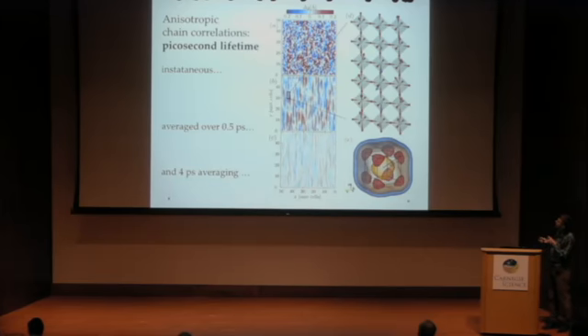Here is the same snapshot, but averaged over half a picosecond. So there is already some averaging, and here you can see there are stripes, which you can think of as polar nanoregions or whatever, which are elongating along the y direction. So these are these longitudinal correlations, which were already understood 50 years ago. But what is important is if we do even longer averaging, let's say over 4 picoseconds, the intensity, the contrast fades out. So it means it's something which is short-lived. It exists over the time scale of a picosecond.